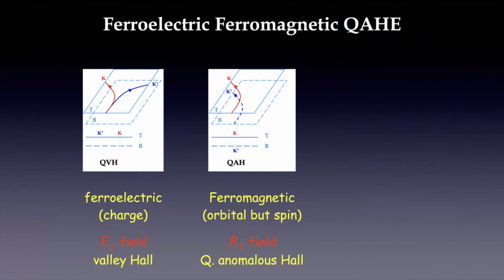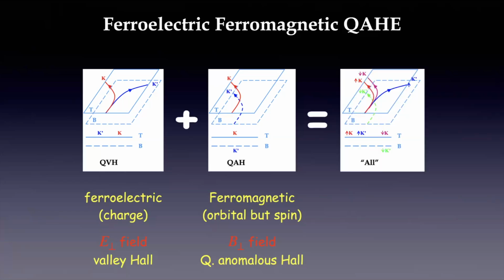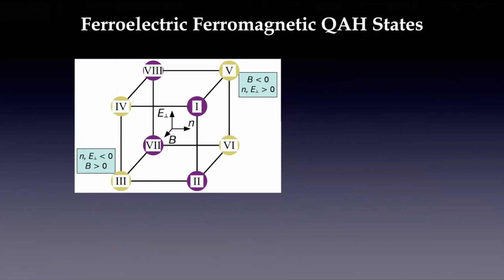Okay. So I'm going to talk about a particular one, which is the most interesting, and which was realized recently in experiment. So what about if one spin has this ferroelectric order, and the other spin has this ferromagnetic order? So that can combine together, it will become this phase. It's kind of like a partially layer polarized phase, right? So once we realize that there is a Chern number inherited from this phase, this spin, then following the Streda formula, density can also be a tuning parameter of the system. Okay, so combining the electric field, magnetic field, and the density, this very special phase, the quantum anomalous Hall state, is kind of like an octet, 8 of them. Okay, because we can use the three parameters to tune that.